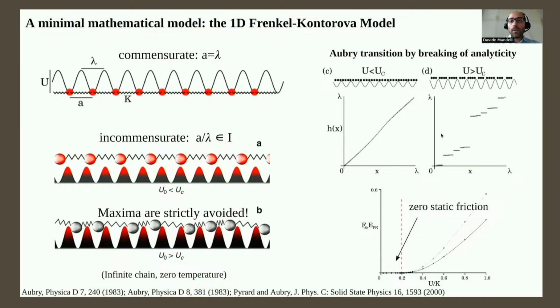From the tribological point of view, this transition corresponds to a transition from a state of exactly 0 static friction, that has been mathematically demonstrated, to a state of finite static friction, and the transition is actually continuous, or second order, so static friction increases continuously at the critical point. The existence of this 0 friction state is due to the existence of a 0 frequency phonon mode, or phason mode, that adiabatically connects an infinite number of equivalent ground states. So this suggests that by building incommensurate crystalline structures, there is the possibility of achieving states of very low friction